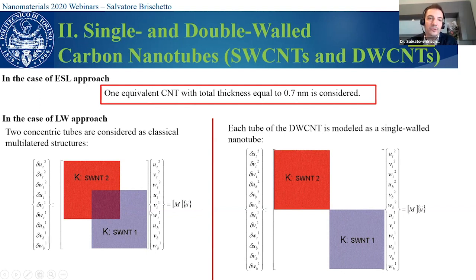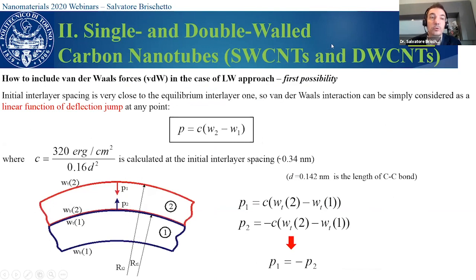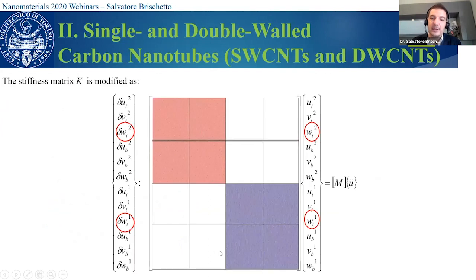In the case of a layer-wise approach, we cannot consider this type of assembling because they are not multilayered structures with interlaminar continuity conditions, but they are separated. But if they are separated, the two nanotubes are not linked between them. We must introduce the van der Waals forces in order to collect the rigidity of the two single-walled carbon nanotubes. So the idea is to include the van der Waals forces in the layer-wise approach. These are the typical equations that we have seen. And these equations, a first possibility, give these two forces, which means adding these terms to our assembling in this way. So in this way, the red block and the blue block are connected between them.